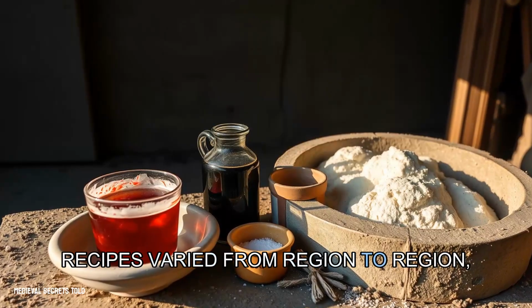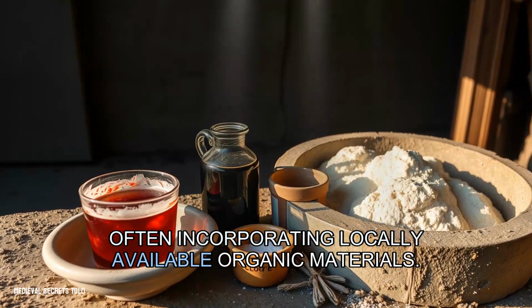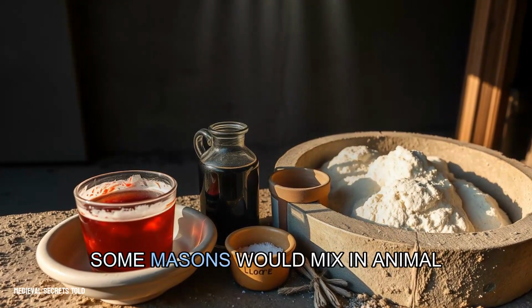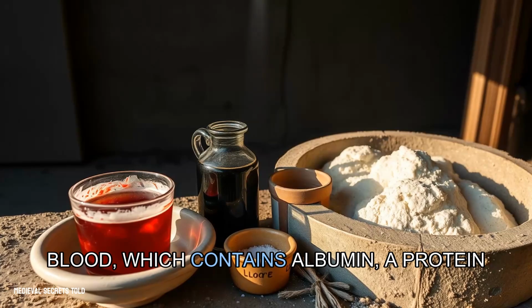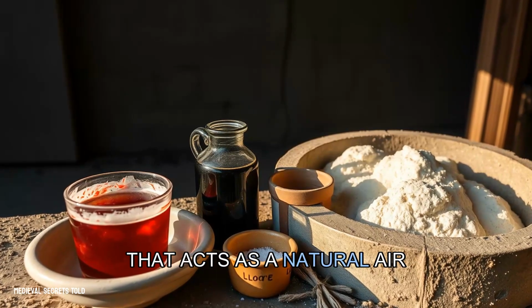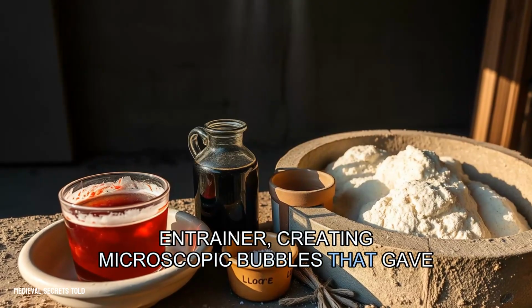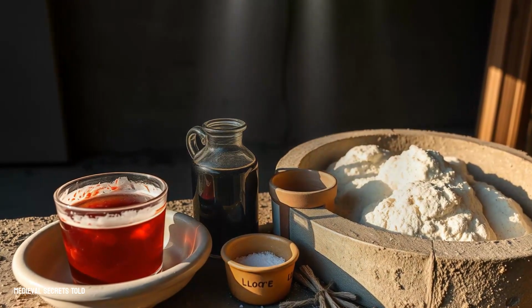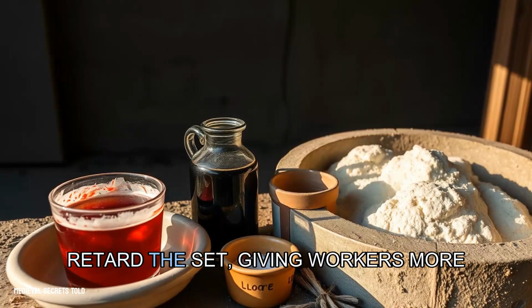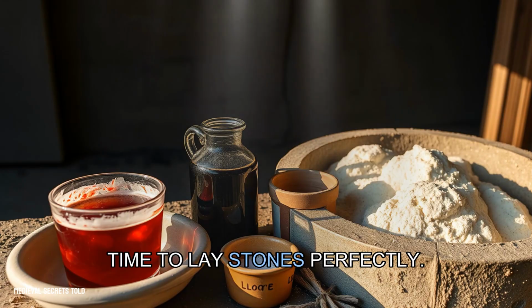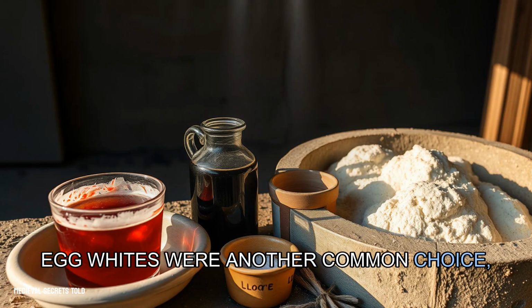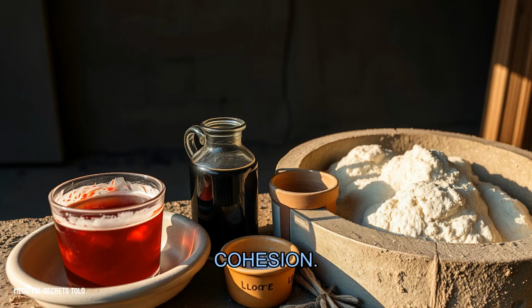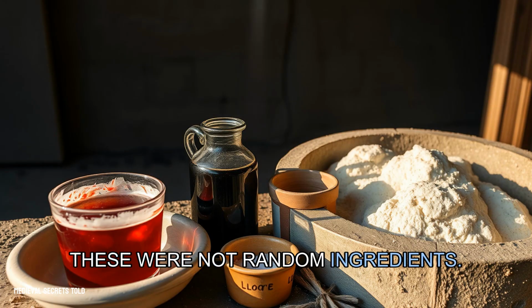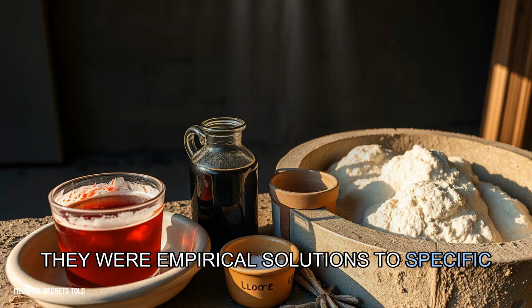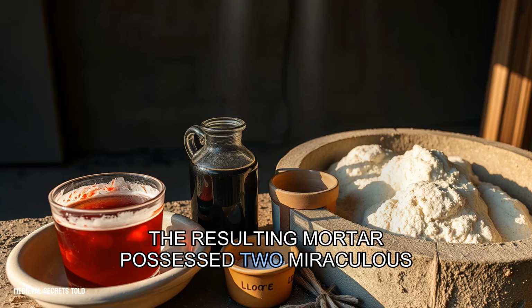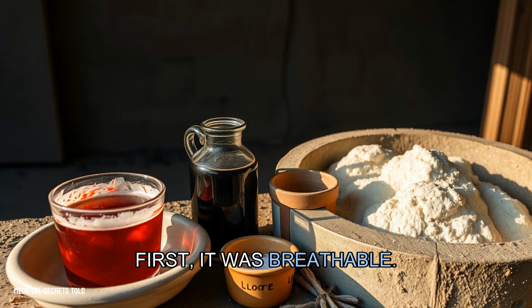Recipes varied from region to region, often incorporating locally available organic materials. Some masons would mix in animal blood, which contains albumin, a protein that acts as a natural air entrainer, creating microscopic bubbles that gave the mortar flexibility. Others used beer, whose sugars helped retard the set, giving workers more time to lay stones perfectly. Egg whites were another common choice, providing a binding quality that increased cohesion. These were not random ingredients, they were empirical solutions to specific problems. The resulting mortar possessed 2 miraculous properties. First, it was breathable.